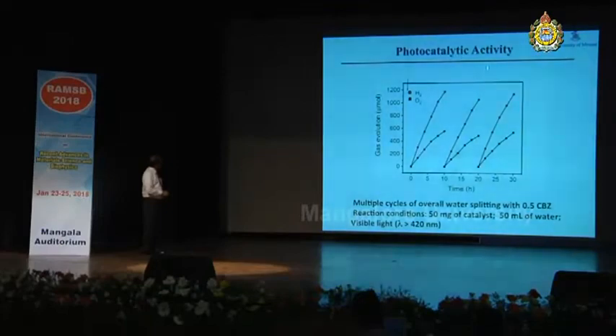And the photocatalytic activity also we have tested to understand the overall water splitting using this compound. We just tested with this sample 0.5 CBZ, reaction conditions like 50 milligrams of this catalyst and 50 milliliter water and the visible light. We could get this data and the time versus the gas evolution is shown.